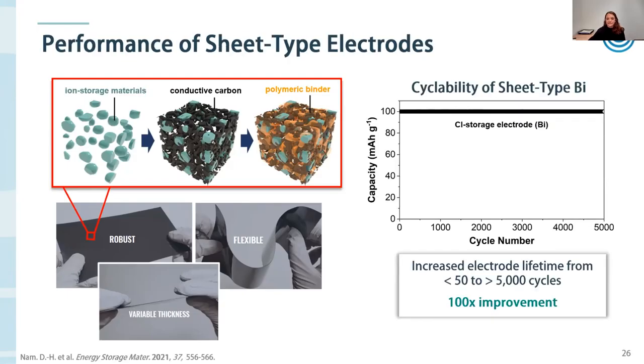And so using these electrodes, we can now see stable performance of our bismuth electrode for over 5,000 cycles. We've gone up to 8,000 cycles now. These tests are actually running for over a year, and we see no performance degradation. So through this really intensive optimization process, we've been able to increase the lifetime of our bismuth electrode from less than 50 to over 5,000 cycles.